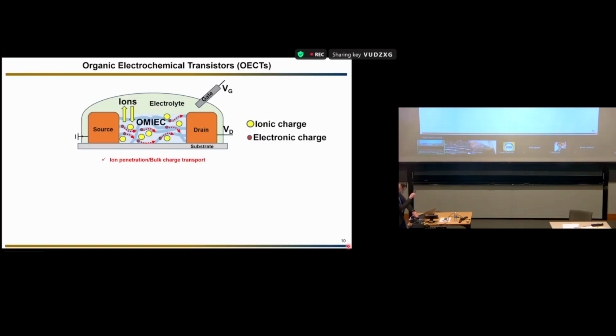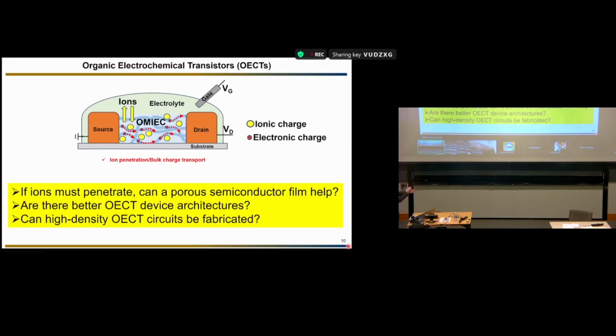So you have an OECT, you want to have ions going in and out, okay? There are a few important questions that come up. One is, if ions have to penetrate, instead of a typical dense film, which is used in any semiconductor device, can we use a porous film? Can we get better ion movement in and out? The second question is, are there different types of OECT architecture which can solve some of the processing issues? And the third one, can we create high-density OECT circuits? Here you have a liquid, so it's very difficult to have very large integration when you have a liquid as a dielectric, as an electronic insulator.